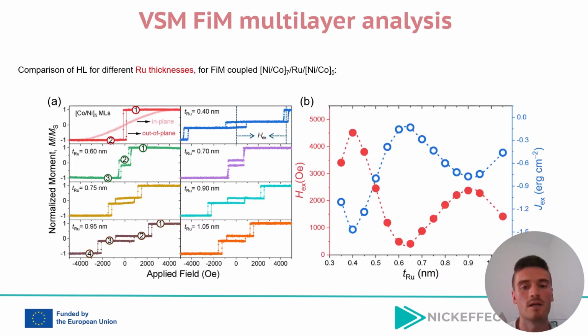Next up, we show a complete vibrating sample magnetometry characterization of ferromagnetically coupled multilayers with 7 bottom ferromagnetic cobalt-nickel repetitions and 5 on top, focusing on the effect of the ruthenium spacer thickness for this given ferromagnetically coupled multilayer heterostructure.